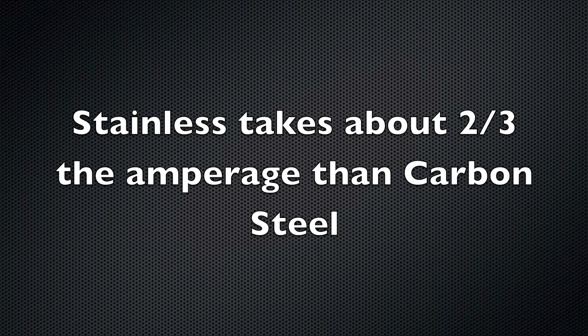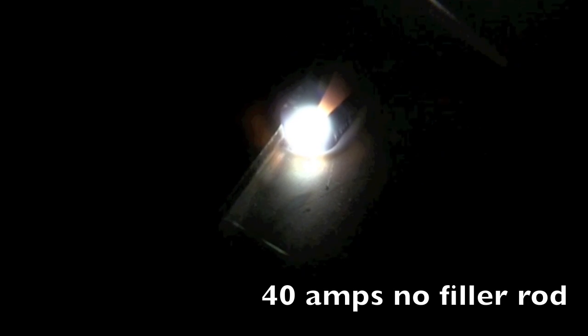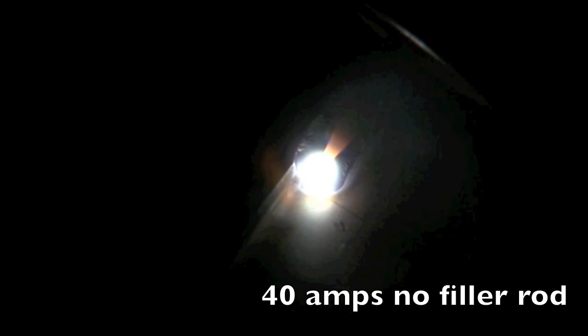All right, there is a rule of thumb that says that about 1 amp per 1/1000th of thickness will get you in the ballpark. Well, that's really based on carbon steel. Stainless doesn't need that much amperage. It only takes about 2/3 of an amp per 1/1000th. So one way to set a machine is, especially if you don't have any good numbers on the dial, or if you don't feel like it's that accurate, or maybe there's a pair of vice grips instead of an amperage knob, figure out the amperage it takes to do a fusion weld without filler metal, and then add about 10% to that with filler metal.